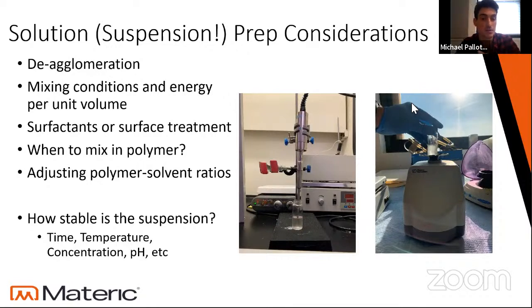In some cases, to avoid any agglomeration between nanoparticles, we'll use a surfactant to make sure that the dispersion happens correctly, or a surface treatment such that the particles will repel each other and stay away from each other in solution so that we don't run into any clogging or strange viscosity or uniformity issues within our solutions.